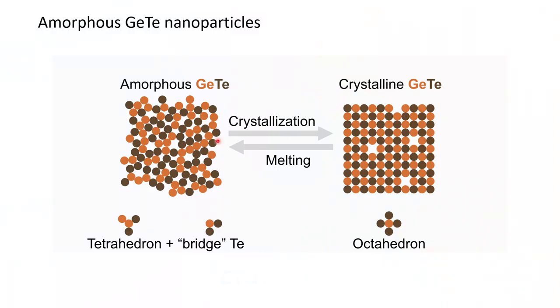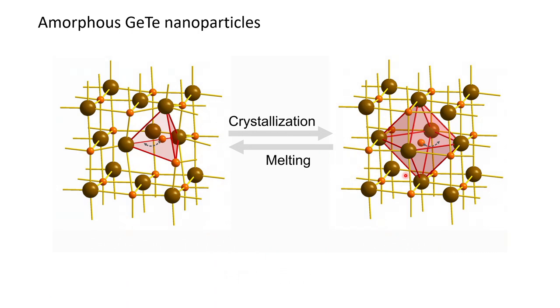So essentially, the crystalline and amorphous structures should be just distorted enough to have different transport properties, but they should be close enough to switch back and forth fast. And then we were looking into the 3 dimensions here, and the answer is surprisingly simple. To switch between the amorphous structure and the crystalline structure, one would need to move only a single atom, only by about 2 angstrom. This is this germanium atom in the middle.